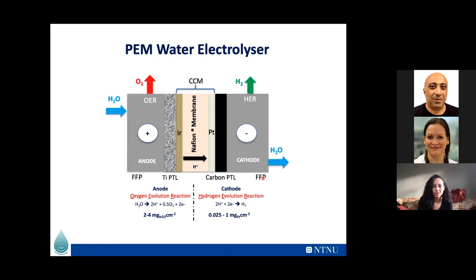They both have pros and cons. One would be much more expensive than the other, or less durable. So for example, PEM water electrolyzers are very expensive, but more durable, so they can last a bit longer. Alkaline water electrolyzers are obviously much cheaper, by a factor of 10, but durability is not that great in comparison to PEM water electrolyzers.